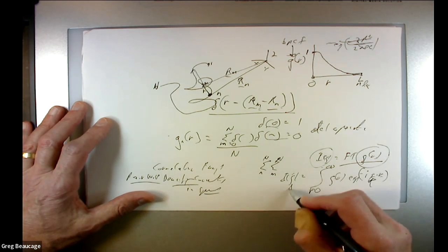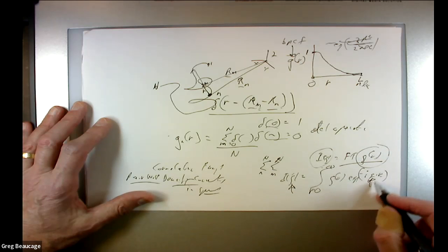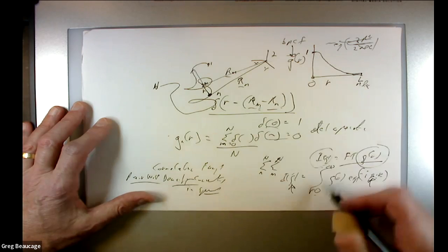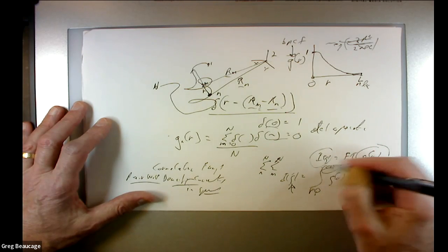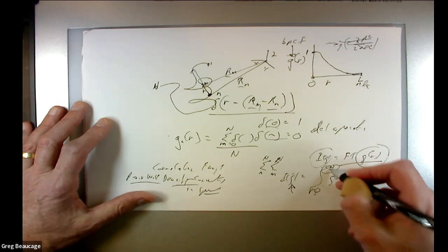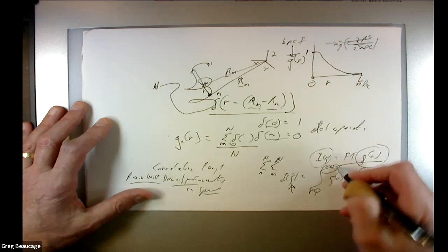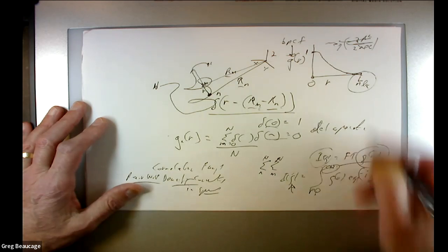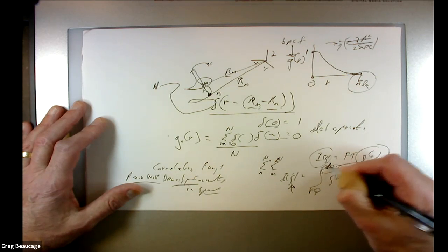So you pick a value of q, like 0.01 inverse angstrom. You plug in 0.01 inverse angstrom, and you run through that correlation function over all space from 0 to infinity. This infinity is a little bit of a problem, because you have to figure out a way to extrapolate. But for us, infinity isn't a problem because the chain ends at L, so this is actually to capital L.